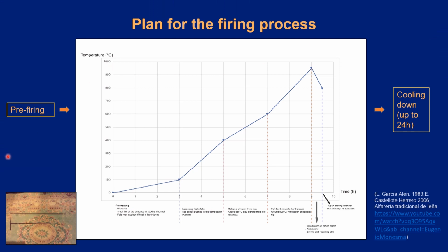For the pre-firing session, first of all, we will do a pit fire to dry the combustion chamber and the stoking channel. In the second session, we will fit the central pillar and the perforated floor to prefire it for 7 to 8 hours to let the water in the clay evaporate slowly.